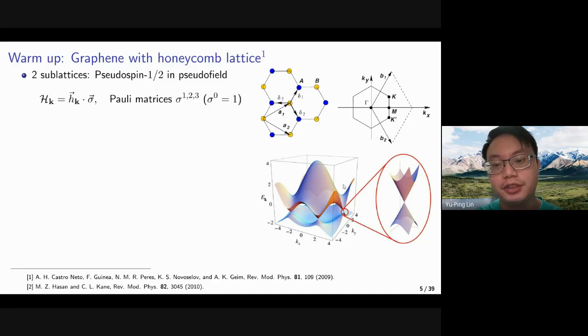So the band structure looks like this. We have a particle band and a hole band, where the 2 degrees of freedom correspond to the two sublattices. And also, there is a particle-hole symmetry. That is, if we look at the hole band, it could be obtained by just reversing the sign of the particle band. And a particularly interesting point is at the charge neutrality, where you can see that there are two inequivalent valleys at the K and K prime points, where K prime is just negative K.